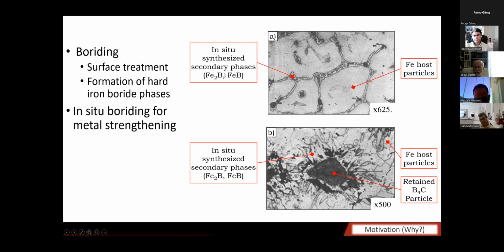We have used the same phases, not as surface enhancing phases, but as in situ strengthening. So our approach might look like the same physical and chemical phenomenon is happening, but it is different because we are using it for in situ synthesis of iron boride phases, which will eventually strengthen the matrix. Here are very old but very important studies from the literature in which iron particles have been in situ synthesized by iron boride phases. This approach is similar to ours, but again, no control on the morphology, no control on the formation of these secondary phases.